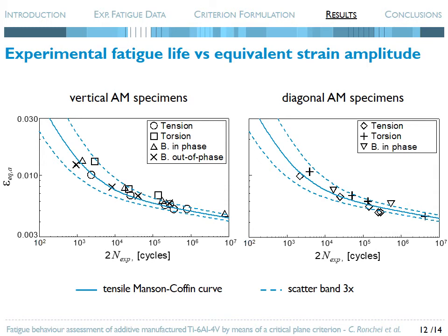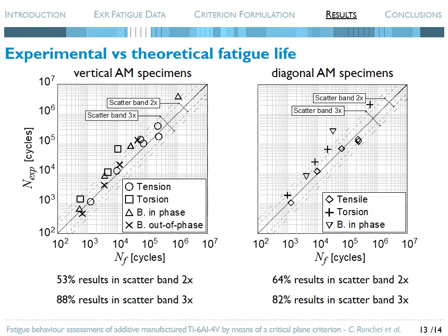As a matter of fact, only 12% and 18% of the theoretical results related to vertical and diagonal AM specimens, respectively, fall outside scatter band 3x. See the blue dashed lines in the present figures. The comparison between experimental and theoretical fatigue lives for both vertical and diagonal AM specimens is shown in present figures, where the solid lines indicate a perfect correlation between experimental and estimated fatigue lives.